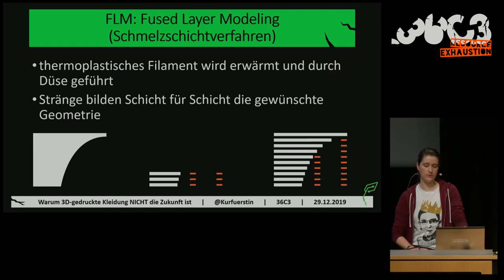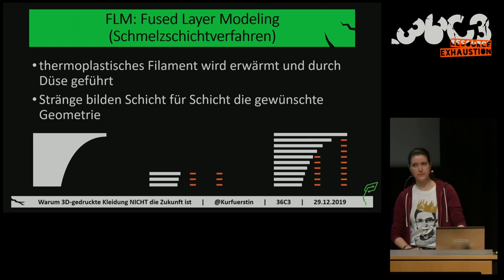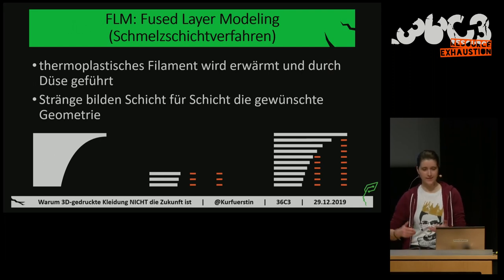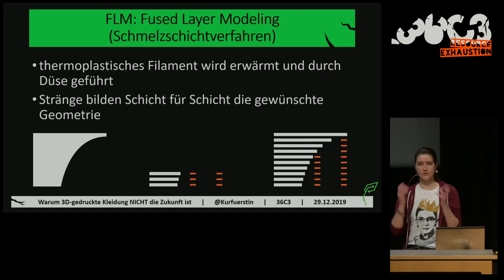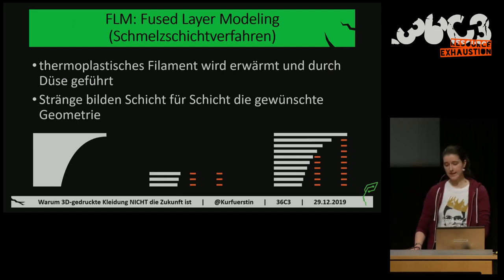And if you have an object that hangs over, like you see on the left, you need some pillars to help it stand, and that pillar structure needs to be built from the beginning and is in the finished object, and you have to remove it afterwards. That's no problem if it's a hard enough material, you can just break it off. But if it's elastic, you can't really break it off. If you pull on it, it just elongates, and you don't really win anything. So if you try to build geometries like that with an overhang, that method doesn't really work for it. You don't win any time or get anything out of the method like that.